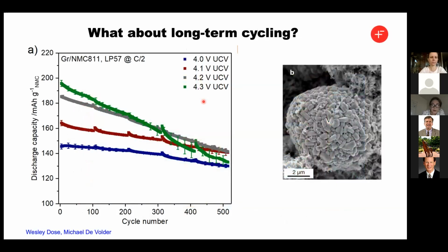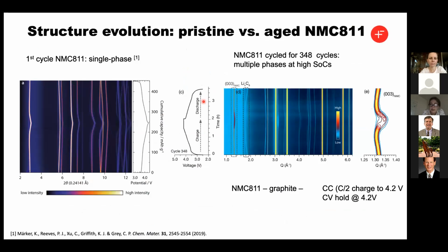Okay, I'm going to rush through by saying we've also done experiments where we cycle things for long durations. And so we look at what happens to the diffraction after multiple cycles. So this is after 348 cycles. We have a cell and we periodically look at it in the beam time, at a number determined by the synchrotron scientists, not us. And you can start to see this broadening of the 003 peak that tells you something about the spacing.